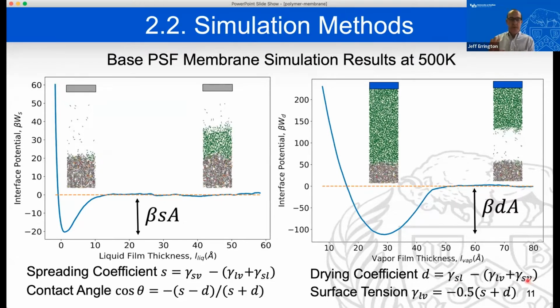So a couple things to note is that once you have the spreading coefficient and the drying coefficient, either one of them in combination with the liquid vapor interfacial tension could be used to determine the contact angle. If you go through a process in which you do both a spreading calculation and a drying calculation at the same state conditions, then the combination of those two can be used to determine both the contact angle associated with a fluid droplet at the surface, as well as the liquid vapor interfacial tension.